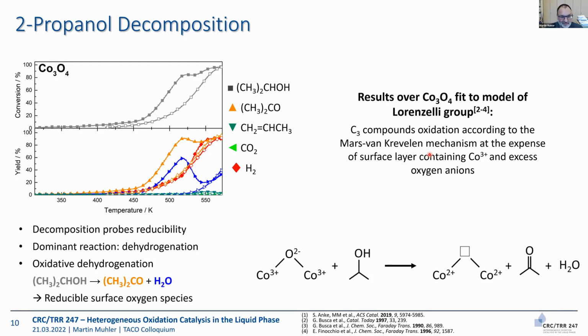Last experiment, what happens when we heat in 2-propanol only? Answer, nothing at lower temperature. Then we do observe formation of acetone and water, clear. Oxygen is taken out from the catalyst, but then we reduce cobalt oxide completely. So we convert the oxide into a metal carbon composite, and that metal carbon composite is then dehydrogenating 2-propanol. That means then we observe the release of hydrogen. So that means we have kind of irreversibly transformed the catalyst into a metal carbon composite.